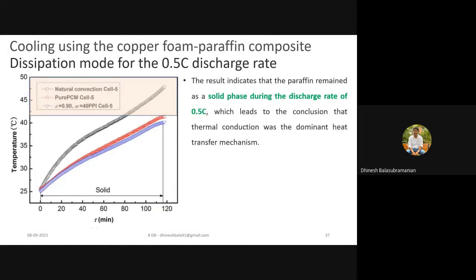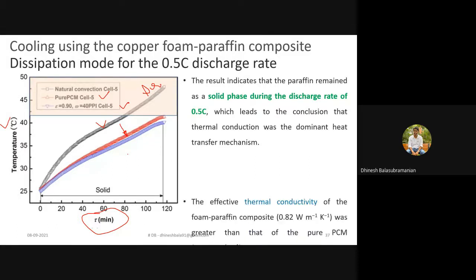And for the further case study, they have come up with introducing a copper mesh into the system. As a huge variation is seen only in the discharge cycle, I have presented only the discharge plot over here. With respect to time and temperature, the black color is where only air is used. If you use only air, the temperature would be linearly rising. And when you make use of the PCM or PCM with the metallic foam, there would be a drop in temperature because of the phase change capability of the paraffin wax.